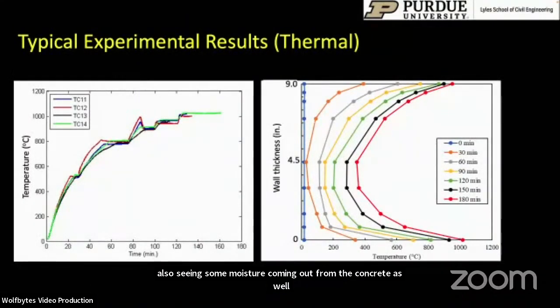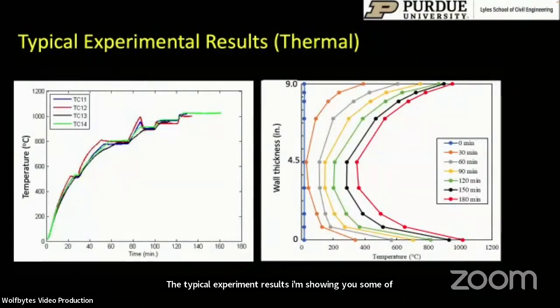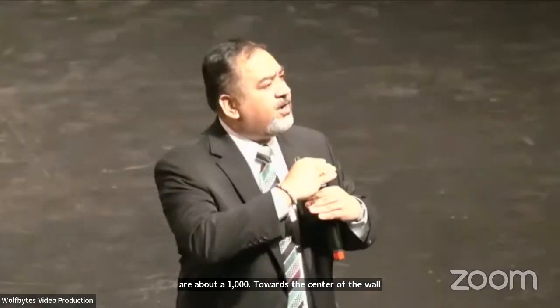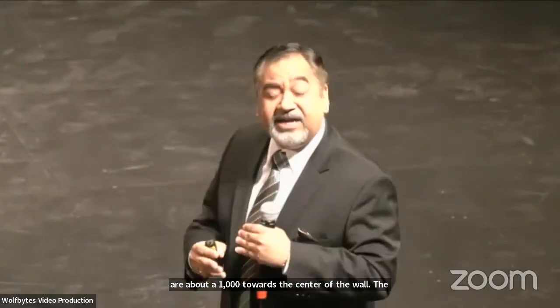The typical experimental results, I'm showing you some of the thermal results. The surface temperature of the steel reaches about 1000 degrees centigrade, which is what you'd want to see in a fire test. But the thermal gradient through that composite section is shown here. While the steel surface temperatures are about 1000, towards the center of the wall, the temperatures are much lower. And this was only a 9-inch thick wall. That's not very thick. It's actually a 1/3 scale model representation of the wall.